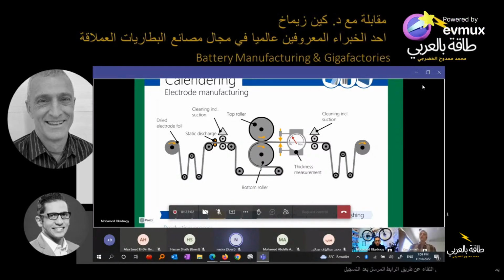And what you're doing is you've coated on this electrode, you've dried it, but now there's a lot of pores left over because you basically evaporated out the water. So it's a little too much like a sponge. And that's fine if you don't care about high energy density. But if you do want to pack a lot of energy into your cell, you need to control the thickness of those. And calendaring is basically you are crushing. I mean, these are big rollers. You are pressing the ever-living snot out of this electrode to a certain level of density.